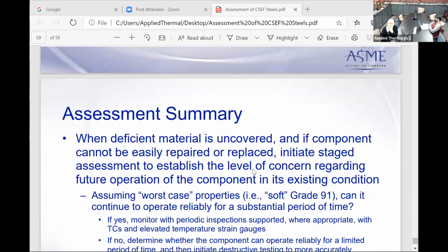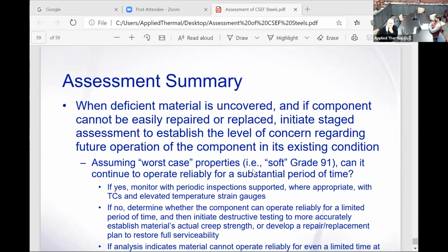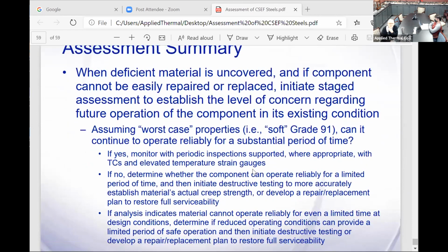So in summary, when deficient material is uncovered and a component cannot be easily repaired or replaced, initiate a staged assessment to establish the level of concern regarding future operation of the component in its existing condition. Assume worst case condition. Can it continue to operate reliably for a substantial period of time? If yes, then you can instrument it. If no, whether the component can operate reliably for a limited period of time, then initiate destructive testing to more accurately establish the material's creep strength.